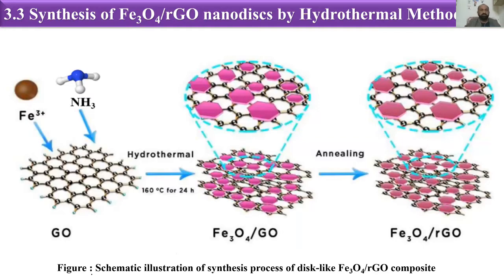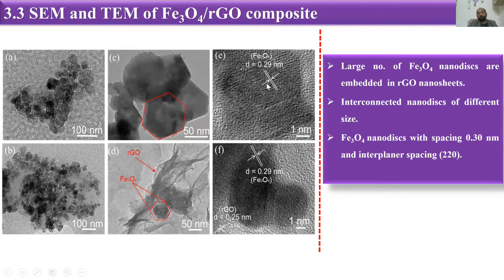Then our third system is the Fe3O4 RGO nano disk made by the hydrothermal method. Again, we have synthesized our Fe3O4 RGO nanocomposite nano disks using the hydrothermal method, and we have got the SEM and TEM from this material, and the HRTEM of the Fe3O4 nanoparticles. We have calculated their interplanar spacing, which is about 220, and which was close to that of Fe3O4 nanoparticles.